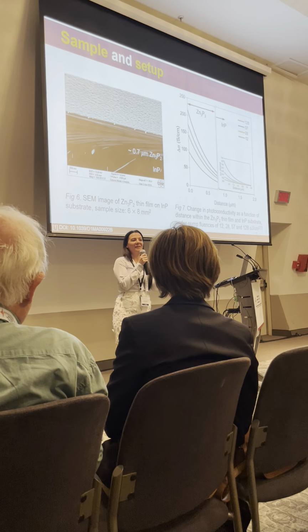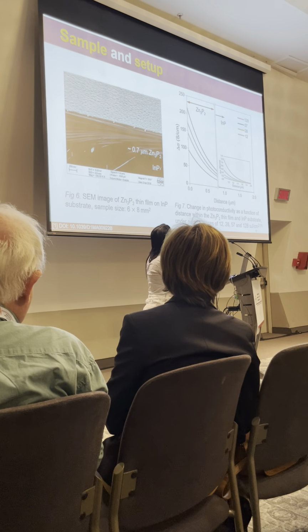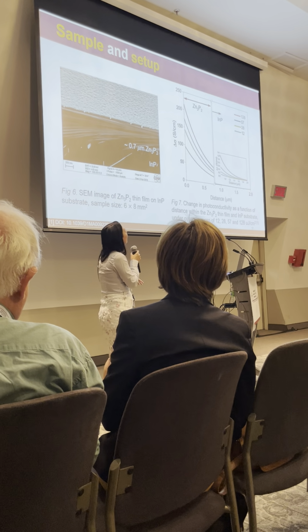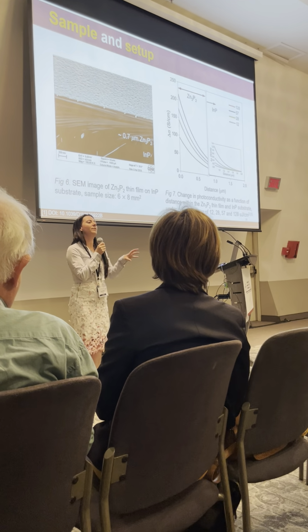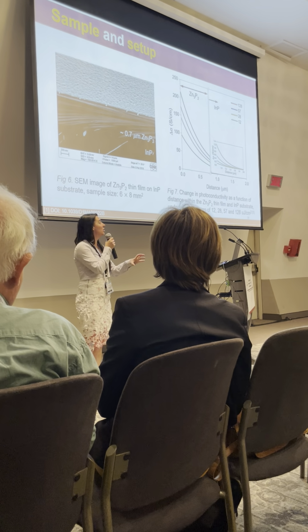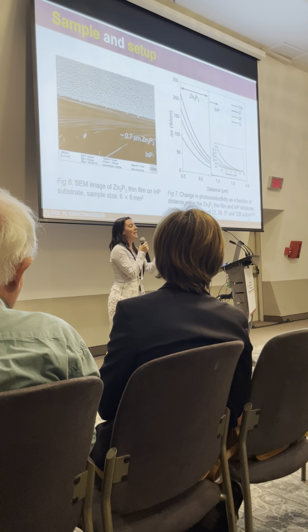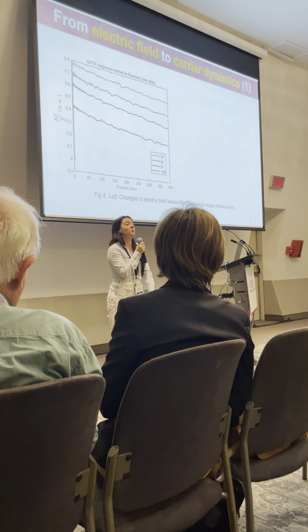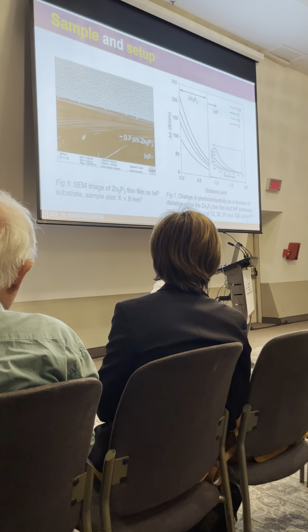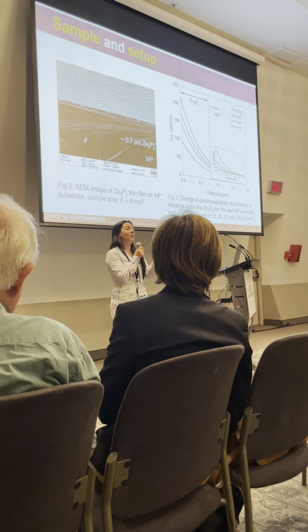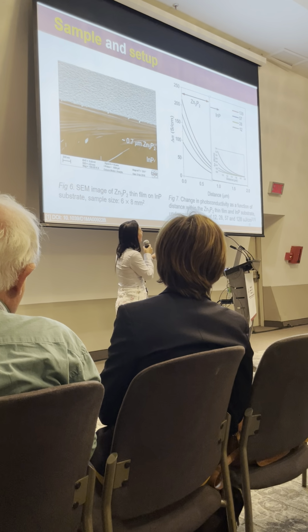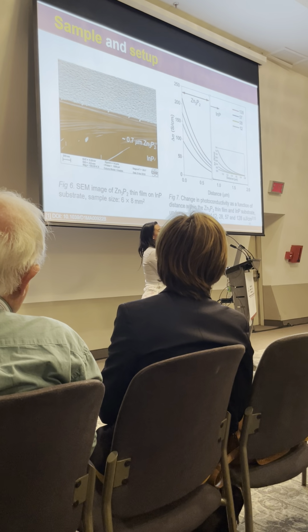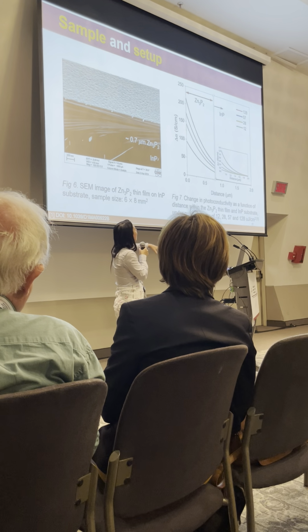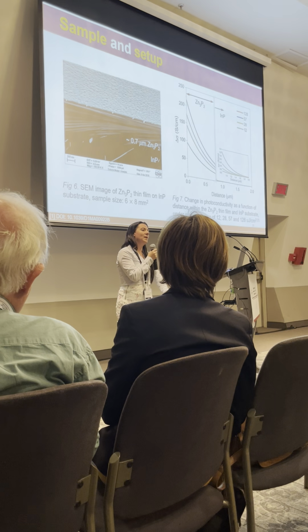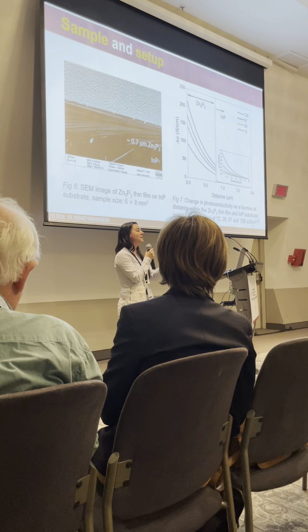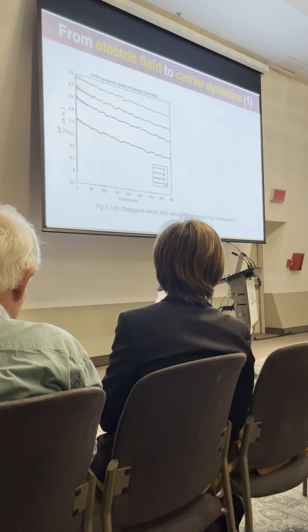So we did check that we were also okay with our assumptions of the thin film approximation. We're actually using the full version of the wave equation to get to our conductivity that I showed you, and we've calculated with a Beer-Lambert law what the conductivity profile should be. This is to prove that we are probing and dominated by the zinc phosphide and not the indium phosphide substrate. You'll see that the indium phosphide substrate is negligible in what we're actually measuring, and using the absorption coefficient, we can say that we've got this Beer-Lambert profile. So that's going into our data analysis when we look at this decay data.